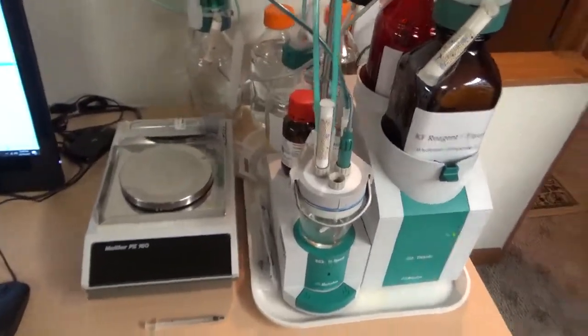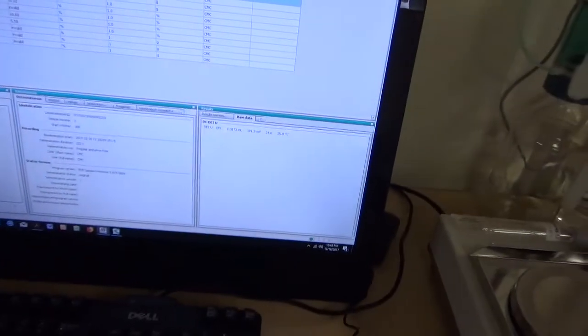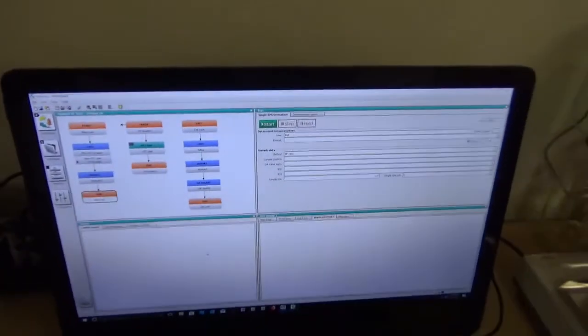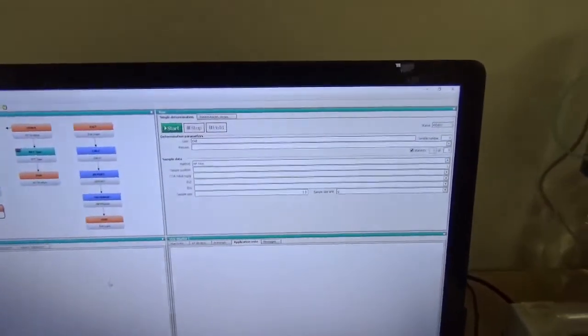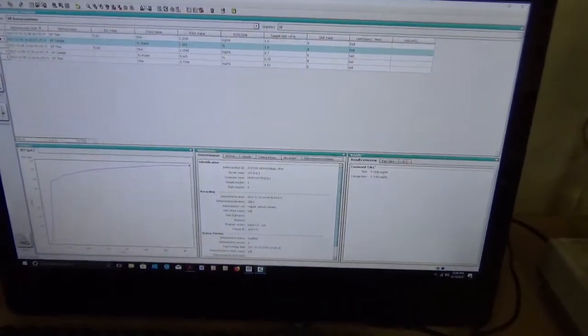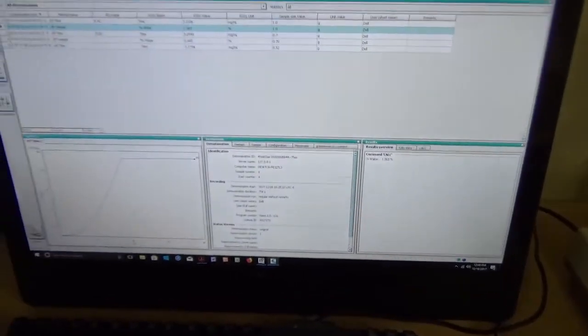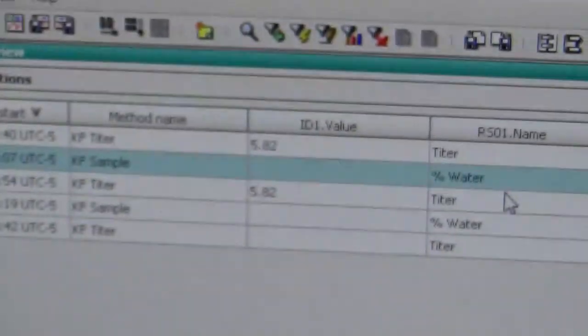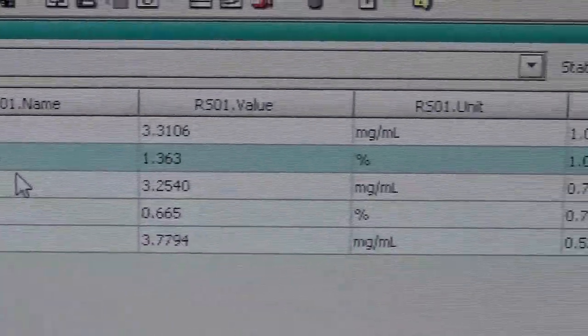And this one is done by Tiamo. Tiamo controls the whole titration. Here we have the method set up to determine the Karl Fischer titration. When we run Tiamo, we collect the data, and it shows the Karl Fischer titration results with the graph, and the data shows the percent water in the sample after we run the sample. We run the titer first, which is the Hydranal Composite, and then we run the sample to determine the water content in the solution.